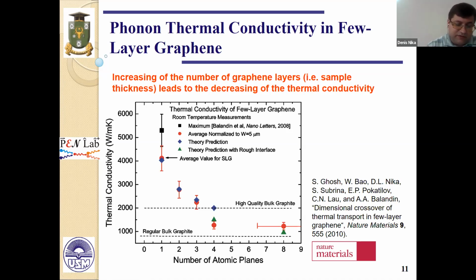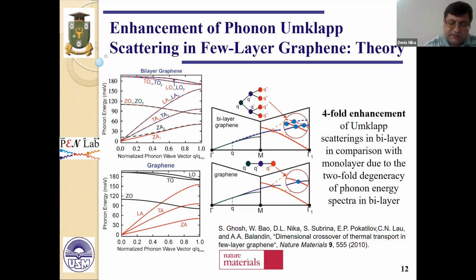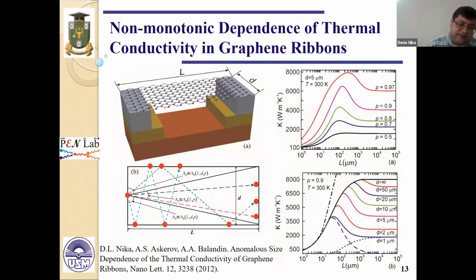Reduction of thermal conductivity with increasing thickness of graphene is explained by the opening up of a new channel for phonon scattering in few layer graphene. Theoretical results on thermal conductivity in rectangular graphene flakes with micrometer lateral sizes are presented in this slide. It is interesting to note that thermal conductivity demonstrates an unusual non-monotonic dependence on the flake length. We explained this by the anisotropic three-phonon scattering in rectangular graphene flakes and angle-dependent phonon boundary scattering.